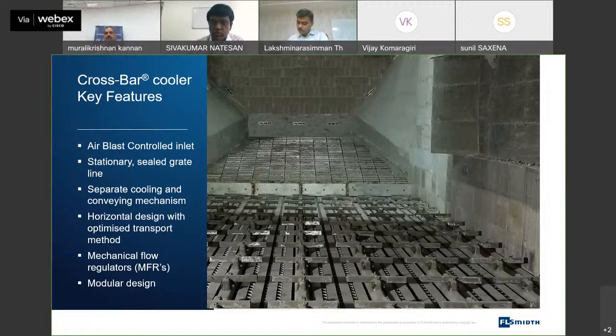But when you move towards more months of operation, if it is a grate plate design where the grate plates move and convey the clinker, the wear between the grate plates increases the distance and the bypass of air. So the cooler efficiency will deteriorate before the next stoppage. It will be performing at a comparatively lower efficiency. But because here there is a separate cooling and conveying mechanism, the grate plates remain intact, and the efficiency of the cooler remains the same.